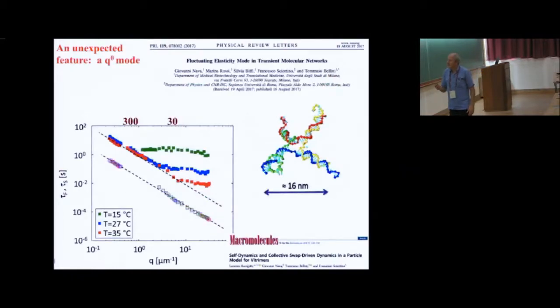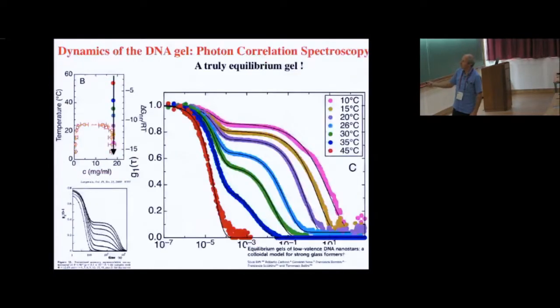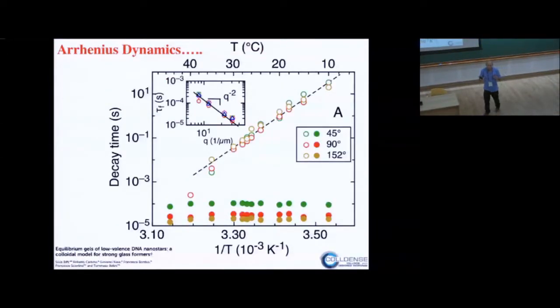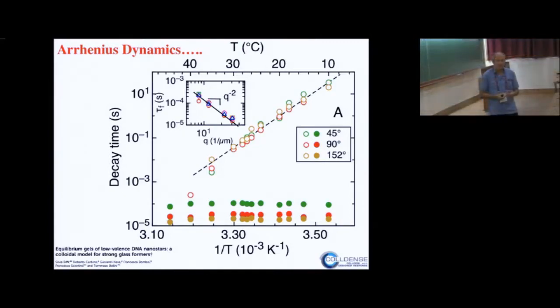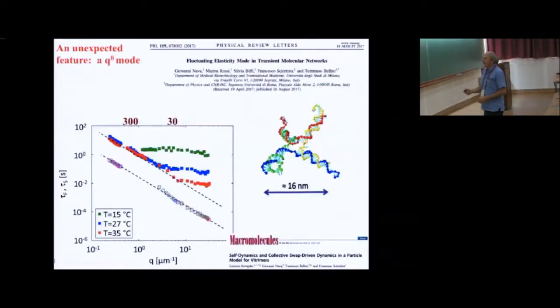There's another interesting physics that we have found. So this was the temperature dependence. If you look at the Q dependence of these characteristic times, remember that the particles are 20 nanometers and the light is 400, 500 nanometers. So you look on very large distances compared to what we do in glass physics, where we look at the cage. At low temperature, you see a nice, very clear Q independence of the alpha relaxation time. So the alpha relaxation time is constant with Q. That's not what you would expect.